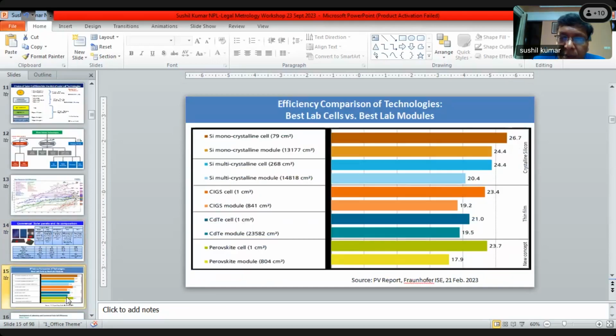If you see, normally always in the lab the efficiency comes more, but when it goes into the module there is a loss of efficiency. Some recent data is given here, like for silicon, monocrystalline silicon, 26.7% is the highest efficiency as of now, and for the module when made it comes down to 24.4, because in the module there is an aperture loss, and also some contact loss. In the multicrystalline 24.4, similarly here also you see some loss is there.